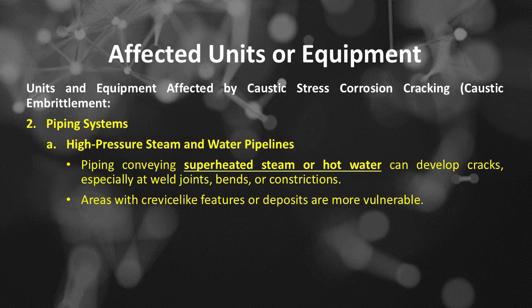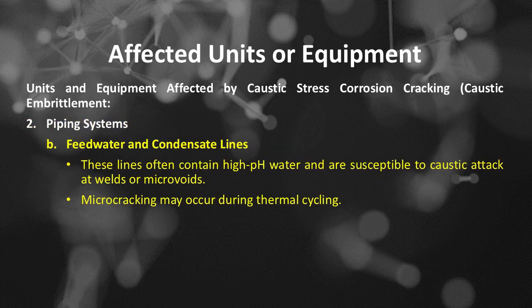Next, number 2 of units and equipment affected by caustic embrittlement is piping systems, which includes, number A, high-pressure steam and water pipelines. Piping conveying superheated steam or hot water can develop cracks, especially at weld joints, bends, or constrictions. Areas with crevice-like features or deposits are more vulnerable. Piping systems number B, feed water and condensate lines. These lines often contain high pH water and are susceptible to caustic attack at welds or microvoids. Microcracking may occur during thermal cycling.